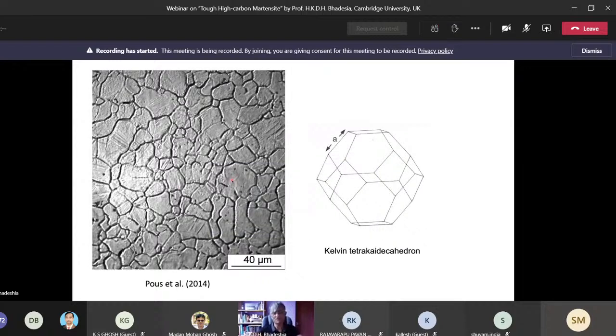Okay, right. Let me show you what an austenite grain looks like in a conventional steel. So this is the grain structure of austenite revealed by doing a thermal grooving experiment where we polish the sample completely flat, metallographically polish it, and then we heat it into the austenite temperature range, and you develop these grooves at the austenite grain boundaries, which reveals their size. And in 3 dimensions, the grains are shaped approximately like the Kelvin tetrakaidecahedron, which consists of hexagons and squares. Okay, and the reason for that particular shape is that it helps to balance interfacial tensions, although not perfectly. It's not possible to get a balance of interfacial tensions in 3 dimensions, so this is an approximation.